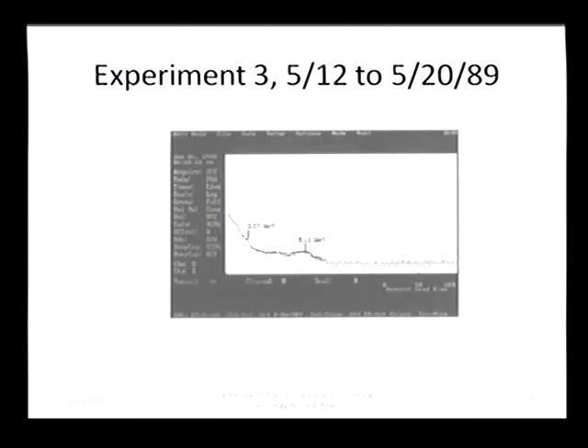It had its Compton edge. This particular peak was due to the fact that the sodium iodide detector was inside of a very thick lead pig that was aimed at the sample. So this is essentially a Compton scatter high gamma, which probably results from the same event. I mean, this looks like a very classical experiment where you have a leaded shield around a sodium iodide detector.